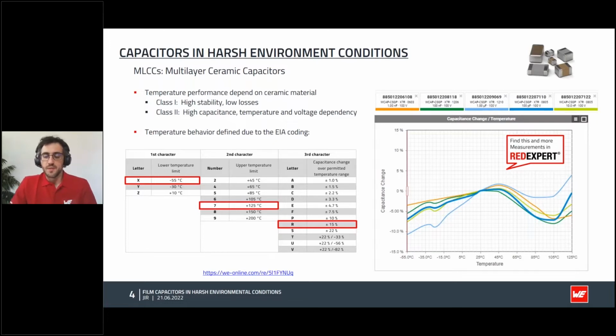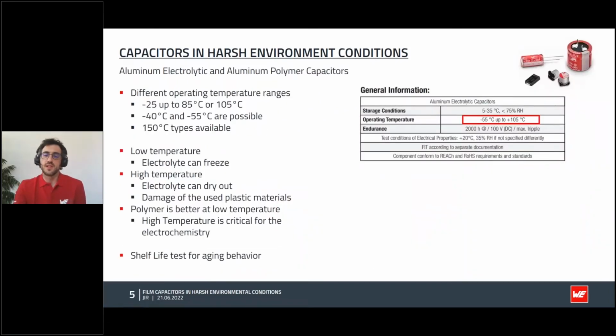Another important thing about MLCCs is the Curie temperature. At this temperature and higher, the material structure changes and the capacitance drops significantly. This temperature is different for each material. For example, it is around 130 degrees Celsius for X7R capacitors, which provides the upper limit of operation of 125 degrees. Now, if we look at electrolytic capacitors, there is a lot to talk about.